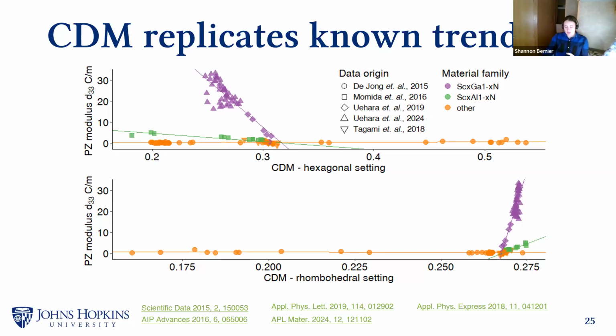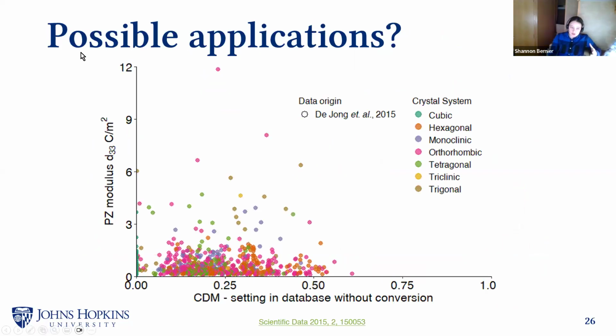There's one other thing I'll say here, which is now that we can apply to different unit cell choices, we did want to test this on a database of materials. However, there isn't really a good database of piezoelectrics. We applied to the Materials Project database, which is all calculated piezoelectric moduli, so it's not experimentally anchored. And there are a lot of errors in that database, missing decimal places, incorrect space group assignments, things like that.